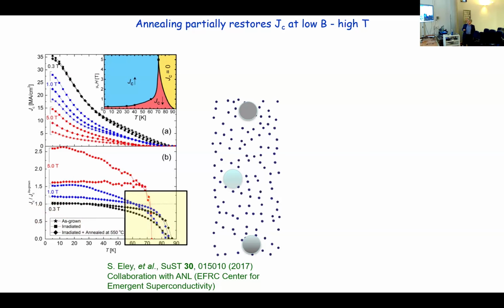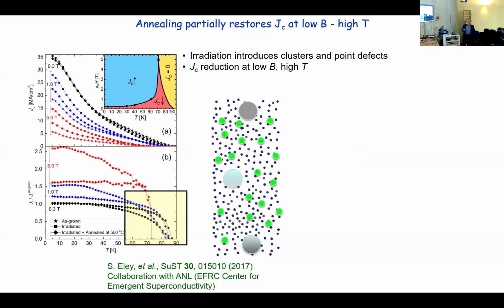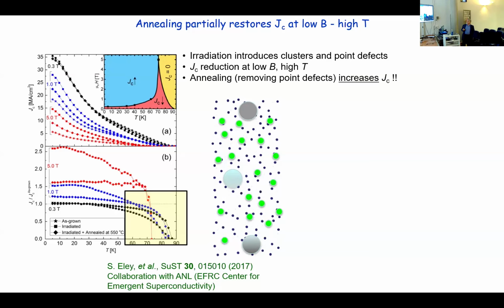So our model is that the initial samples have some clusters. No, sorry, not clusters. These are nanoparticles that exist in the MOD samples and some point defects. And irradiation introduces some clusters and some more point defects. And then when we anneal, we remove some of the point defects, leaving the clusters, and that recovers the Jc. Not totally, but significantly recovers the Jc.